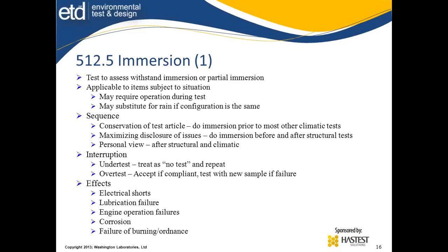The sequence, there's a lot of different philosophies on this. Conserve the test article: do immersion prior to most other climatic events. That way your test article is in good shape. It's likely it'll pass, and it's not subject to causing other damages if it passes. So they conserve the test article to see that no damage gets in there. There's also a philosophy of maximizing disclosure of issues. You do the immersion before and after the structural tests. So now I'm trying to find out, did structural tests affect it?